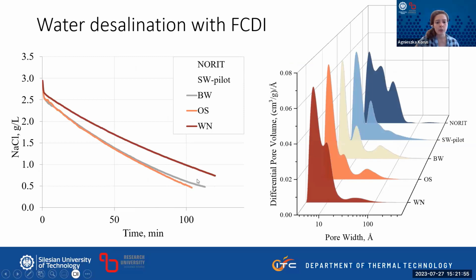Here are the chars that we prepared in the lab. The walnut shells were working slightly worse, and for these three chars, the dependency that a wider pore distribution, more mesopores, is a beneficial thing. We actually could see this trend for the chars that we prepared, because the olive stone and beechwood chars were working better.